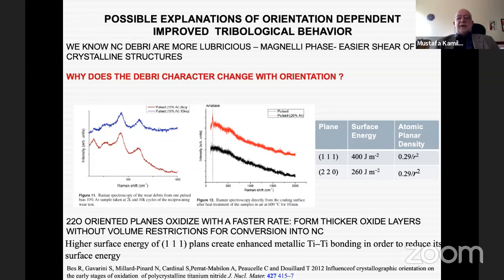Okay, then we ended up with this explanation. When you run the test on a 1-1-1 oriented sample, the temperature that is created during rubbing doesn't allow the formation of a thick surface film because the oxidation resistance of 1-1-1 oriented grains is higher. On the other hand, when you conduct the same test using 2-2-0 oriented films, these films are oxidized at a higher rate, which leads to the formation of a nanocrystalline structure because of the higher volume of oxide material formed on them. So that was the idea, and it's a very good study that shows the role of orientation on tribological behavior and especially also on the oxidation behavior.